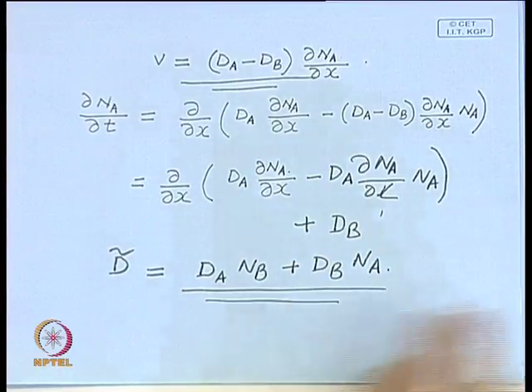Today we looked at the atomistic mechanism of diffusion and saw that when species have different diffusivities, it leads to the Kirkendall effect — marker movement. Assuming no void formation, we derived expressions for the intrinsic diffusion coefficients dA and dB. This is a very important subject; it was difficult to cover fully in two hours, but we will refer to these concepts in subsequent lectures. Thank you.